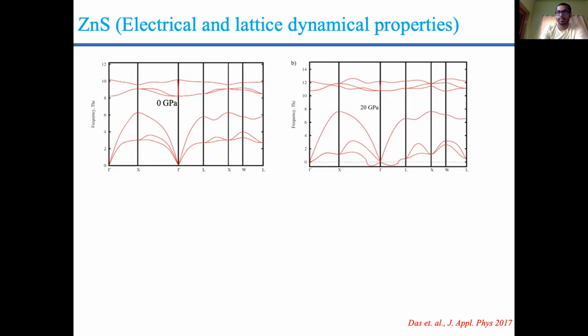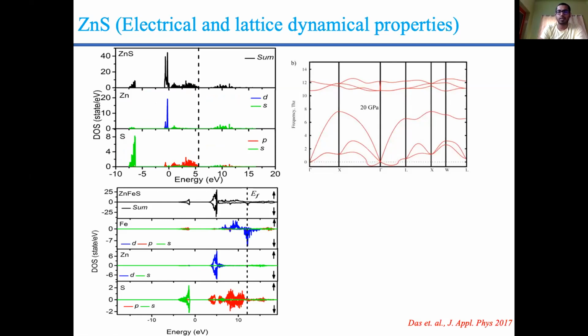Secondly, we are also interested in the electronic properties, because ZnS is already used as a wide bandgap semiconductor. Here we found the band gap is 2.8 eV, which is a little bit lower than the experiments. That's because, you know, the GGA always underestimates the band gap because it overestimates the volume. Later we extend our study with the same study on the iron doped cases.